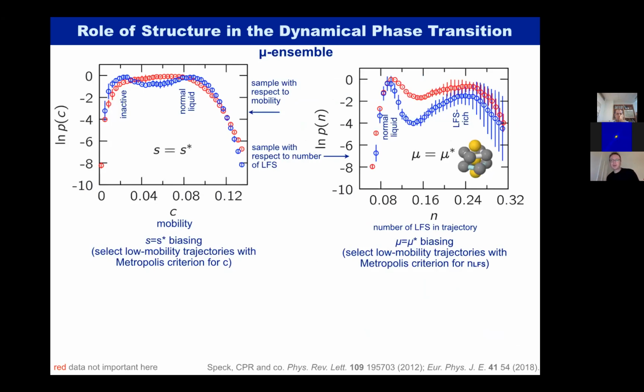The dynamic facilitation theory is built purely on dynamics. We wanted to mix in structure. We have this method, our topological cluster classification, of finding local structure in the material. So rather than biasing the system on dynamics, how much the system moves, we biased on the number of local structures in a trajectory. It's very important that we are biasing this on trajectories, not on single configurations, so trajectories of a few relaxation times in length. And again, we have this dynamical phase coexistence. That is to say, the normal liquid has few local structures in it, but there is an inactive phase which has many local structures in it.